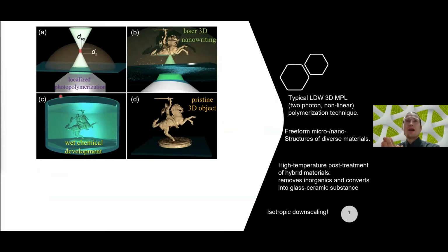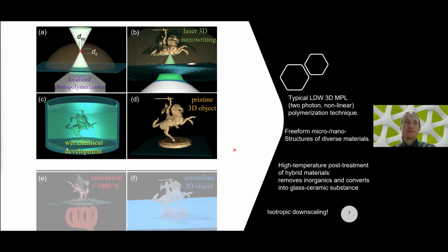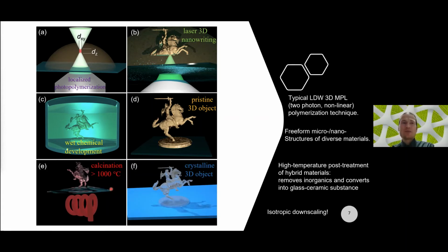So once again, to remind you, we have 3D writing within a resin, a localized photopolymerization, and by following the exposed trace, the 3D objects can be materialized. After developing, they are revealed, and we have a pristine 3D object, which is perfect for making complex shaped objects and for whatever applications. And as mentioned, if we additionally add post-processing at high temperatures and use hybrid materials, we can induce a reaction, or evaporate the organic part and convert it into a crystalline 3D object, still preserving its geometry, and even achieving some isotropic downscaling. Thus, the same technique with additional post-processing can result in metamorphosis of the material, or one could call it some alchemy.